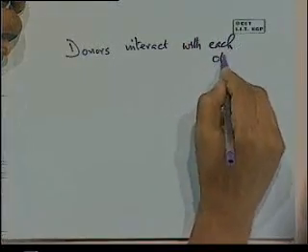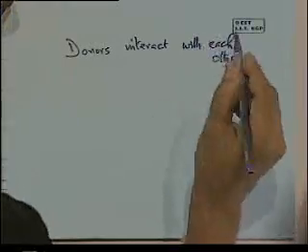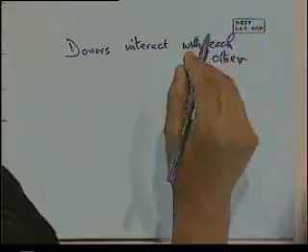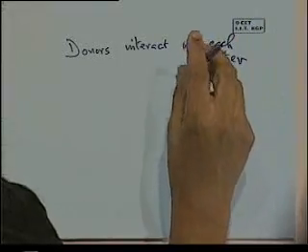When we started, we had doping concentration in parts-per-million — very low concentrations. Now we are putting in so many dopants that instead of one arsenic atom surrounded by a million silicon atoms, the arsenic atoms are getting fairly close to each other. We have interaction between the energy states of the arsenic atoms, just as we saw when bringing two hydrogen or silicon atoms close from infinity. As the semiconductor becomes heavily doped, these interactions become significant and we create an impurity band.